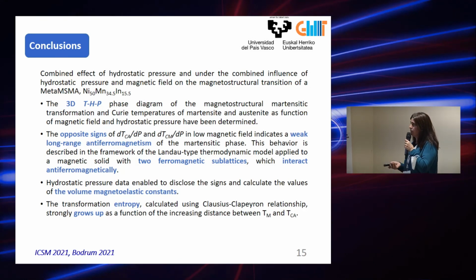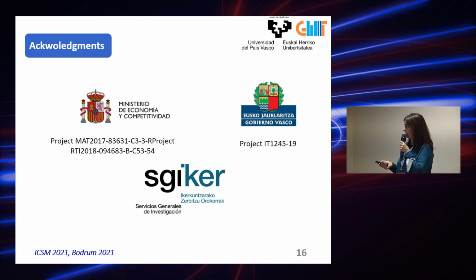Okay, so to finish, some conclusions, only a summary of the combined effect of hydrostatic pressure and magnetic field in this prototype. So we evaluate this 3D phase diagram. That is an interesting result. The opposite sign of this magnetic transformation in the martensitic and austenitic phases gives us an idea that the system is a complex magnetic system, and there is a long-range antiferromagnetic coupling. Also, we can evaluate some different volume magnetoelastic constants with this model, and finally we evaluate the entropy and the dependence of this entropy on the pressure and magnetic field.